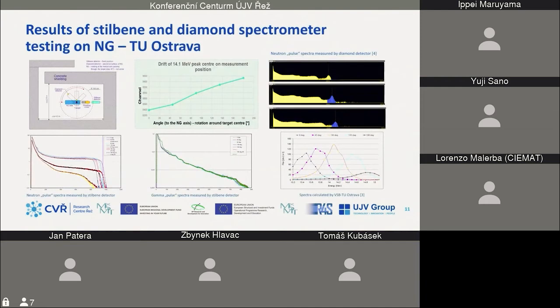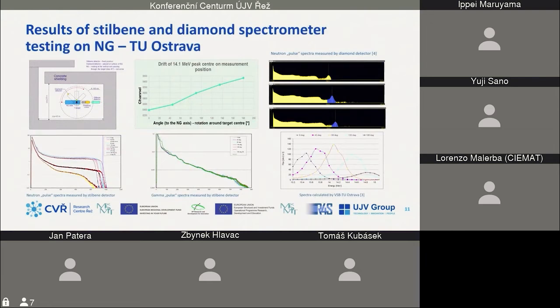The second measurement we performed in Ostrava, at the Technical University Ostrava. The small neutron generator was located under the earth, about 10 meters underground, again with concrete shielding, and we measured the leakage spectra at different angles around the neutron generator and compared with our calculation. In this case, we used the stilbene spectrometer, and the result, the energy shift in the spectrum of the 14 MeV peak, was confirmed by measurement with a diamond detector.